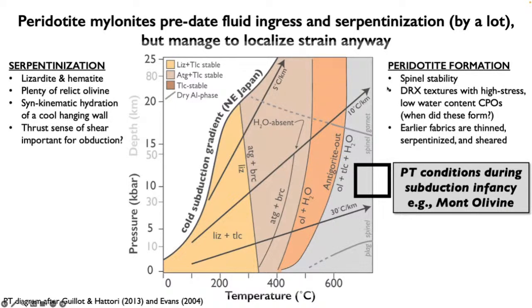So the first thing that I'll come back to is the significance of serpentine. We saw evidence that the peridotite mylonites form before fluid ingress and serpentinization. And based on the temperatures of deformation, we can infer that they form a lot before the ingress of fluids. However, they managed to localize strain anyway. We saw those beautiful shear bands in the dry ultramylonitic Mont Albert rocks, and the incredible grain size reduction by dynamic recrystallization clearly has an important role to play.